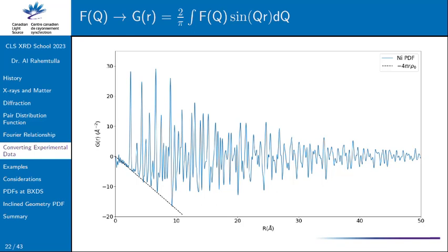So you see this one. I really like this one here. This shows you what the PDF is, the pair distribution function. Let's take the example on the left. The atoms are the coins now, right? And that's the structure. How many coins can you find at the closest distance, which is 2R? That seems like a 9. So you have a peak of height 9 at that distance, at 2R.